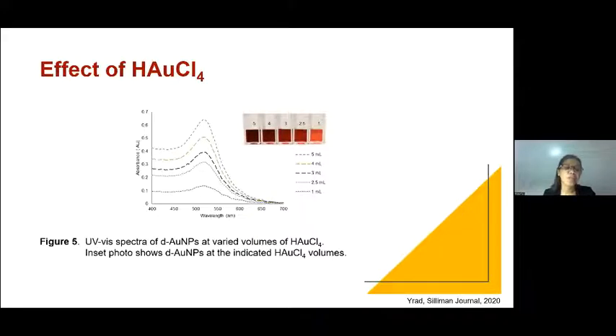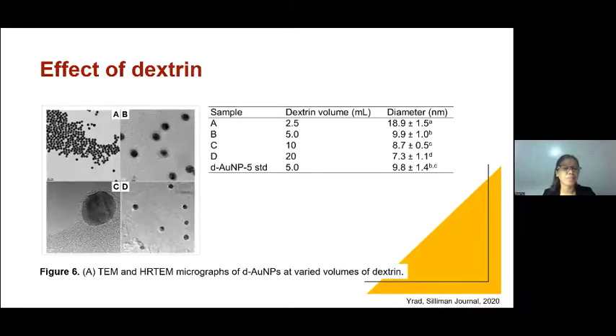Figure 5 shows the UV spectra of D gold nanoparticles synthesized at varied volumes of chloroauric acid. The figure shows the reaction products with decreasing intensity of red color. The decrease in the red color intensity correlated with their absorbance at 520. The results imply that the volume of the chloroauric acid determines the concentration of the generated D gold nanoparticles. Therefore, chloroauric acid was the limiting reagent in the reaction.